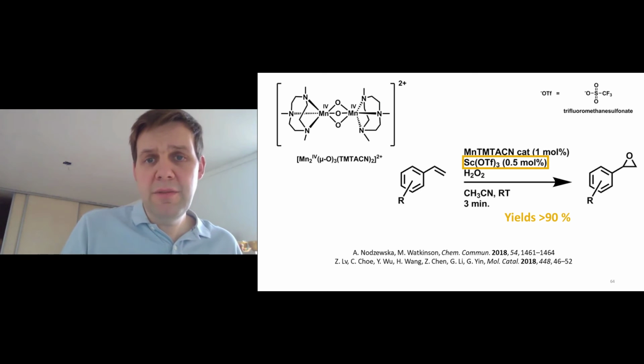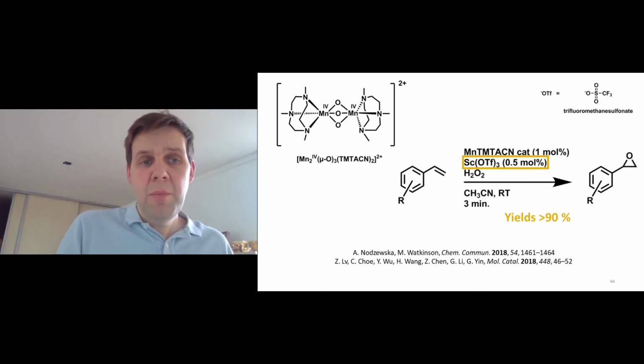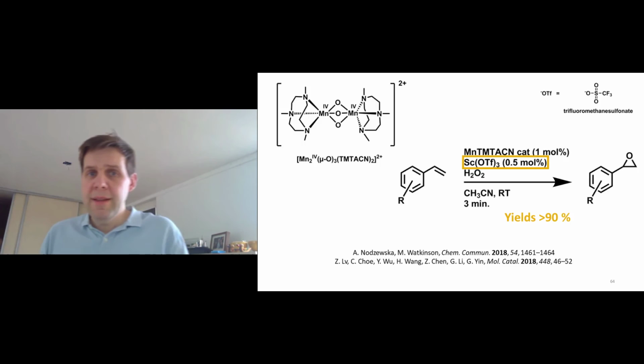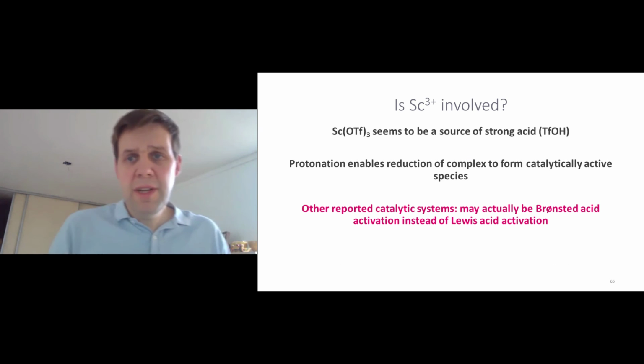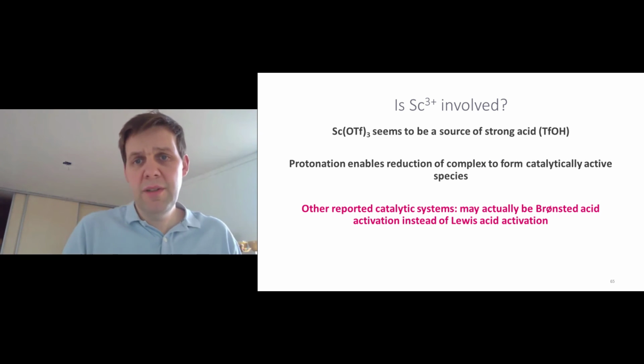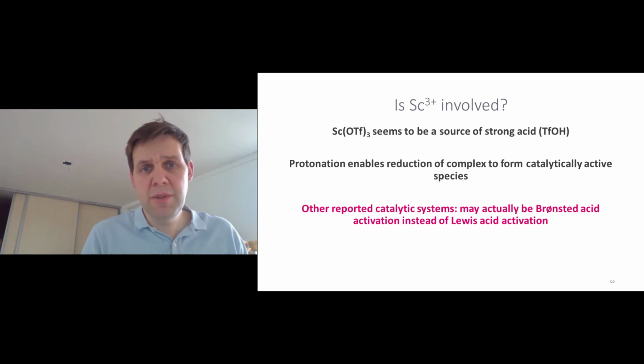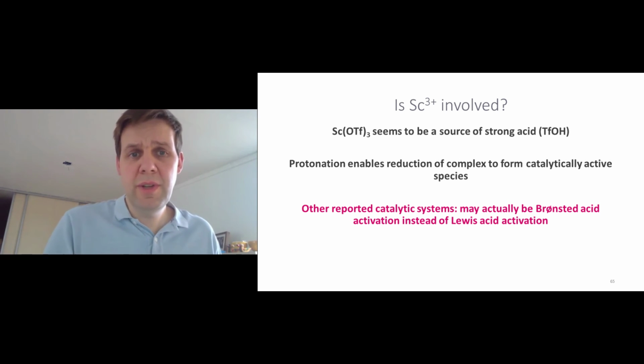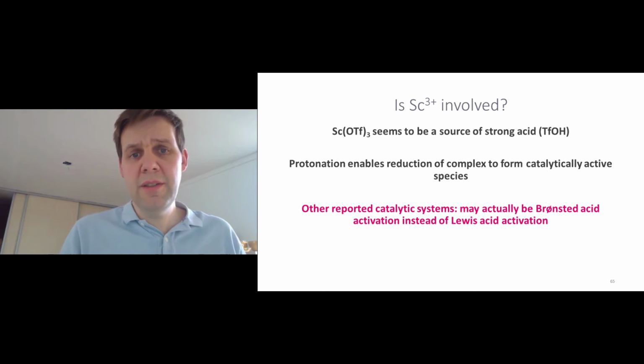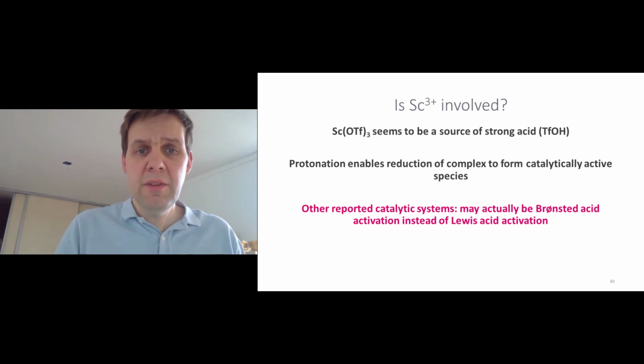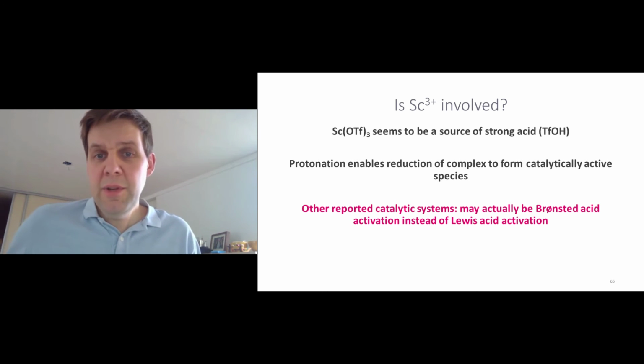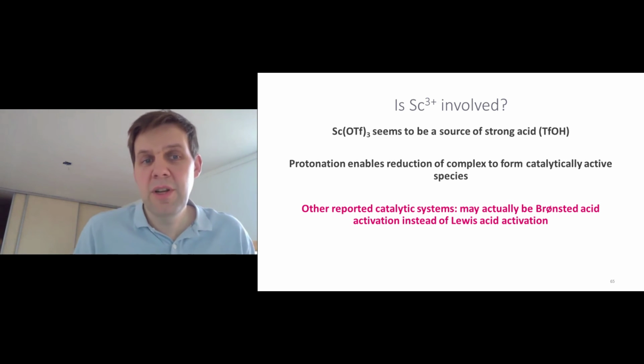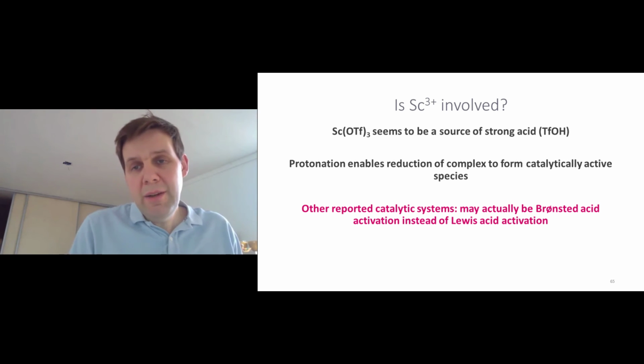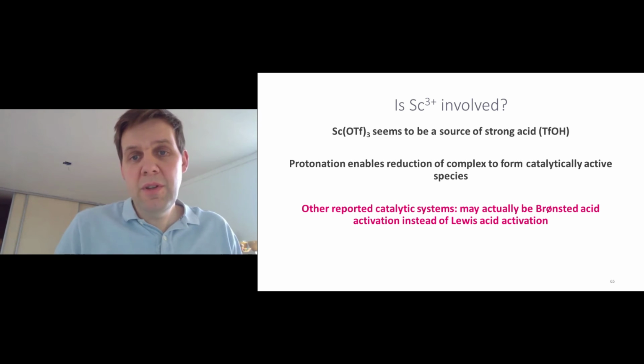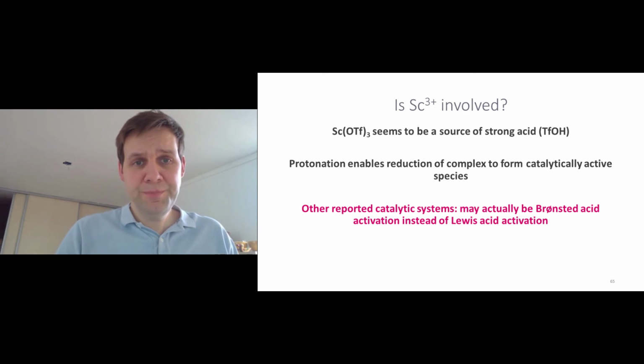And adding triflic acid to reactions is painful. It's a nasty substance, but adding scandium triflate is actually quite nice. But the reality is, scandium triflate is involved as a source of triflic acid and not as a direct coordination to the metal center. So it's not acting in the same way as in photosystem 2. It's actually acting just as a source of triflic acid. And it's the protonation from the triflic acid which is leading to the activity that we see. Now, there's implications for many other Lewis acid activated systems which are reported in the literature. If you look at them, it is very likely because of the conditions that are used, especially for oxidation chemistry, they're actually looking at Bronsted catalysis.